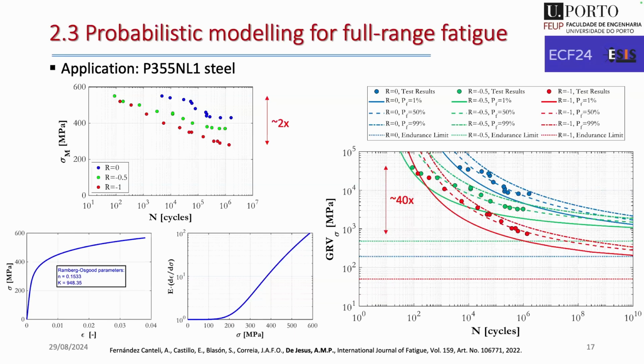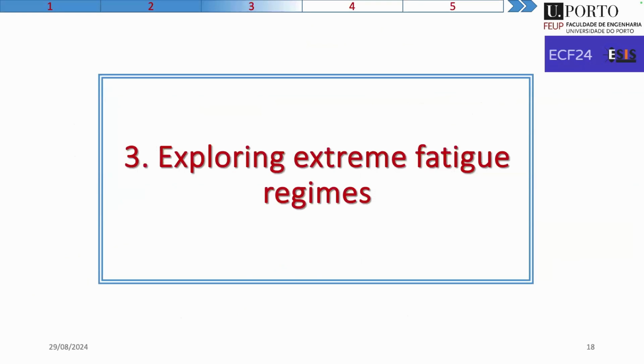In this with the maximum stress, and then we have here a vertical, let's say, range of test data of 2 times. And when we make the transformation I referred previously, we can extend this to 40 times. So we are retrieving the parabolic representation of our GRV field as originally proposed by Fernandez, by Castillo and Canteli. Okay, so these are some experiences regarding the generalization of the existing probabilistic model by Canteli and Castillo.